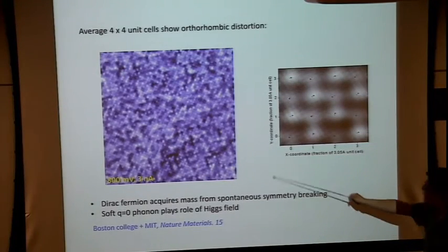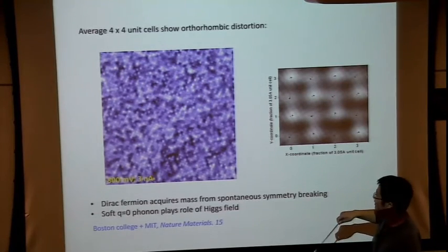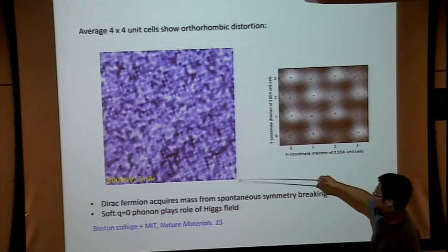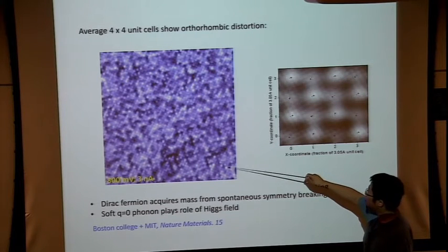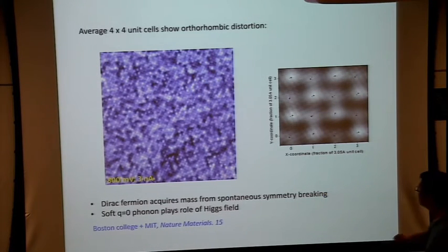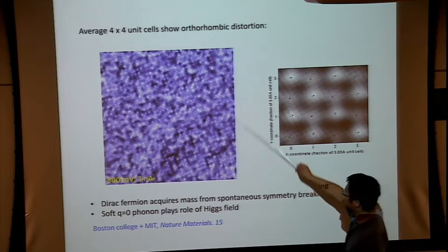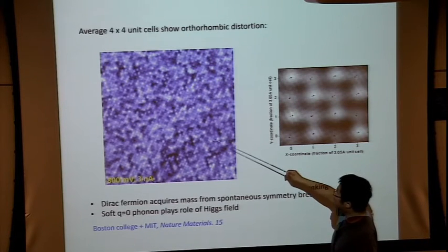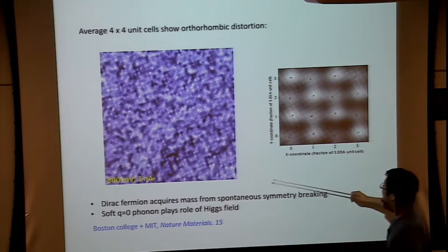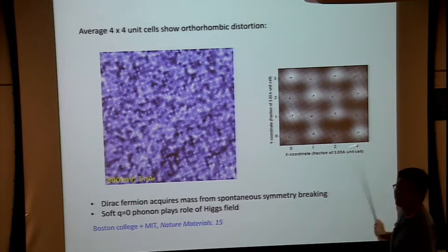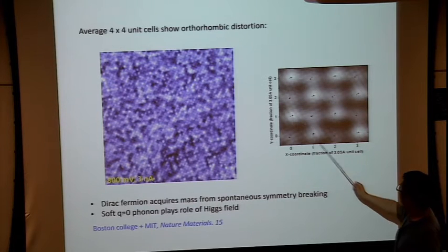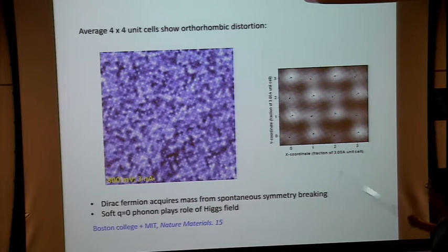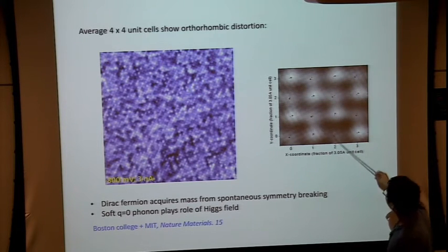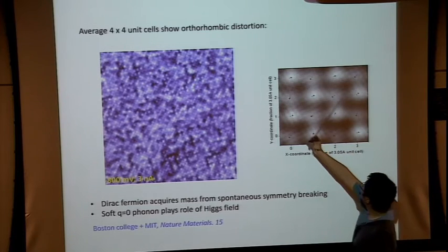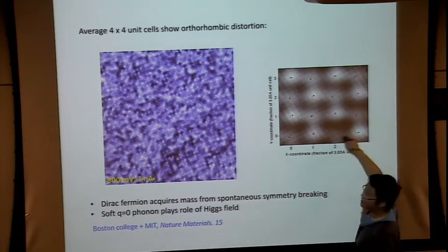And more recently, the Madhavan group continued to improve the imaging topography, and now they can really see the distortion from topography. So again, this looks like a mess because it's an alloy, lead and tin mixed with each other. But if you average over the position of atoms over large areas, you can reconstruct an average unit cell, and you see from this figure this zigzag-like feature, so that this reflection symmetry is still present, but the other reflection symmetry is now lost.